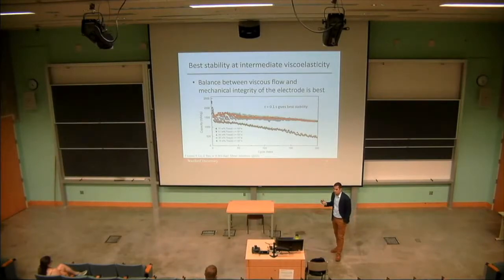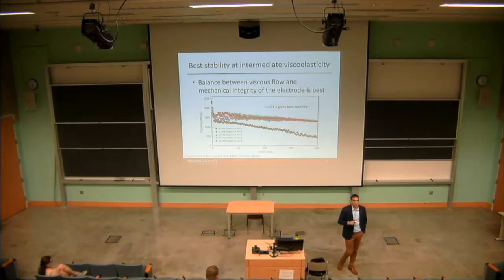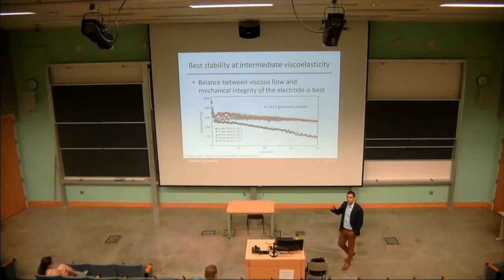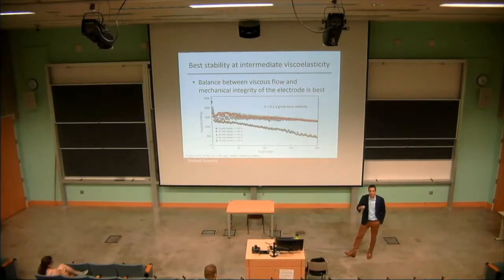And so what this tells us is that there's really a balance between the viscous flow of these polymers and the mechanical strength of the material that's really required for the self-healing binder concept to function. So if you have too solid of a material, the binder in the electrode can't self-heal, and it can't repair itself, and it can't maintain cycling stability. But if you have something that's too soft, too flowable, too viscoelastic, you don't have the mechanical integrity to keep